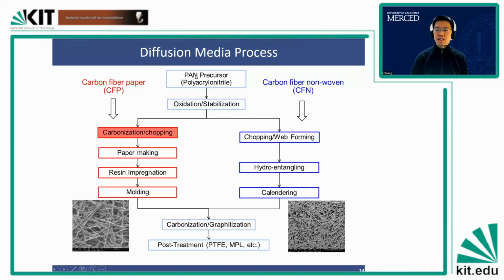You can take a look at this, starting from the PAN precursor to make carbon fiber. And then the process to make it into a carbon paper has, in general, two very distinct routes. I'll talk a little bit about this later on, but at this point, I want you to know that there are two very different processes to make carbon fiber paper. On the left-hand side is mostly the wet process, like paper making, referred to as the wet-laid process. They are straight fibers, and they have chemical binders. These are carbon binders or resins trying to bind the carbon fibers together.